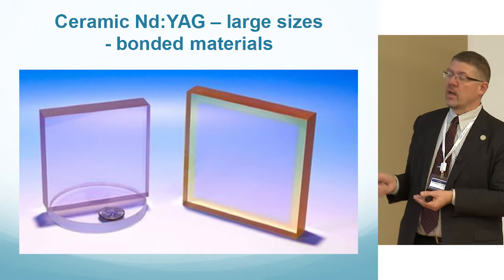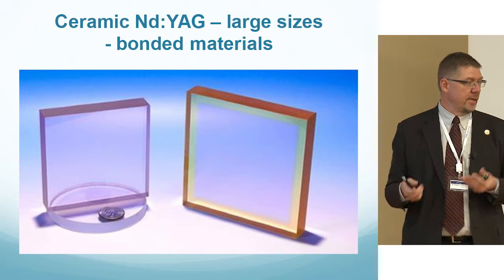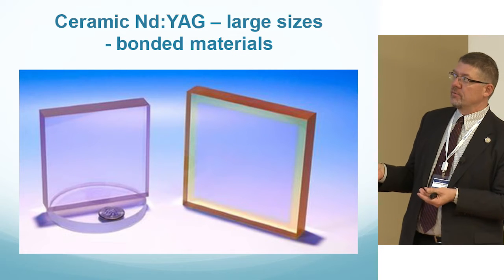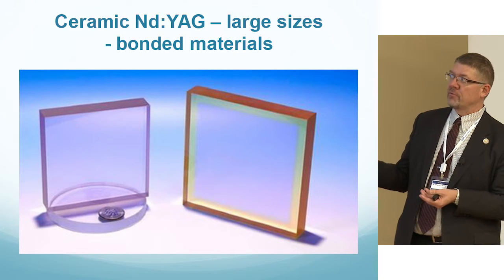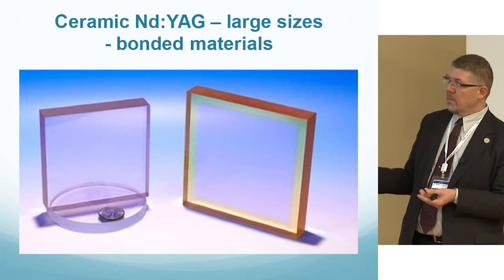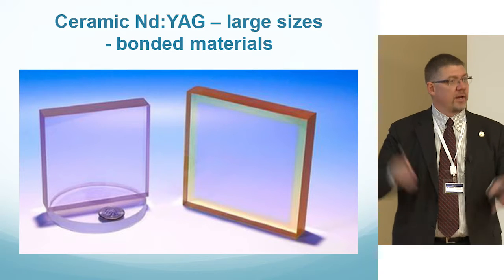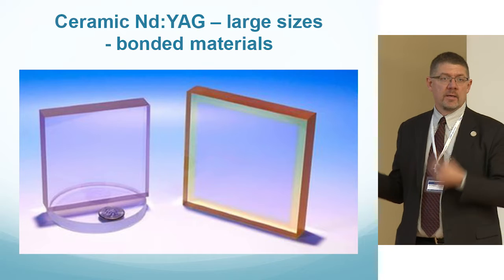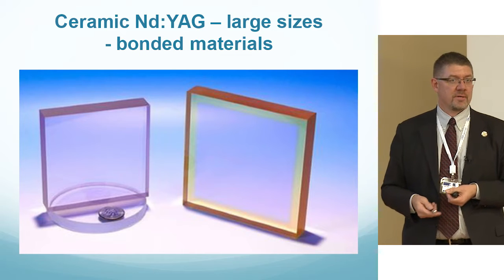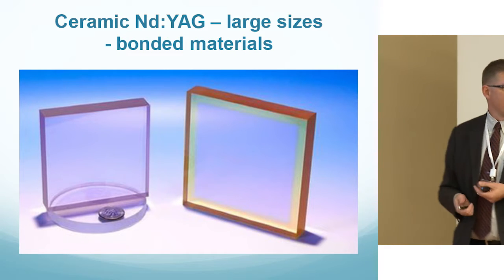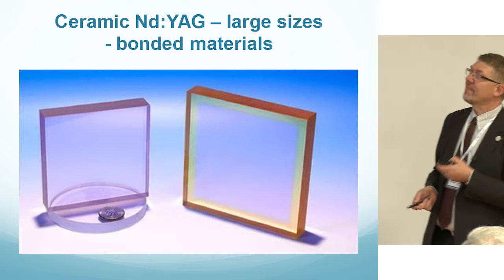Prior to this type of technology, you would have had to do diffusion bonding, which meant take this piece and polish it, get sub-angstrom flatness on all these edges, polish the samarium to sub-angstrom flatness, put it in, heat it up, cool it down, and it's about a 24-week process. So running that through a production cycle isn't very efficient.